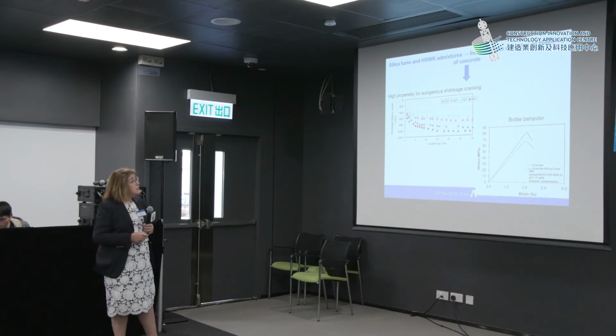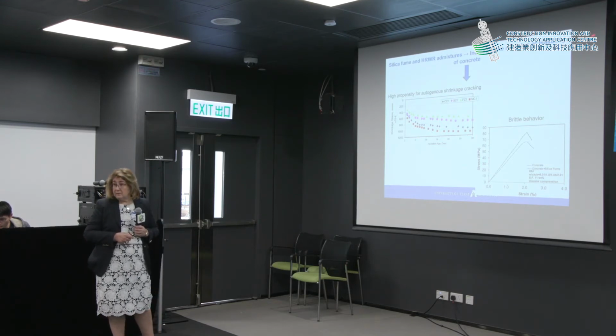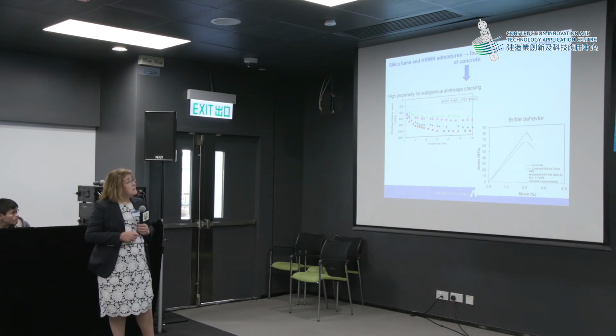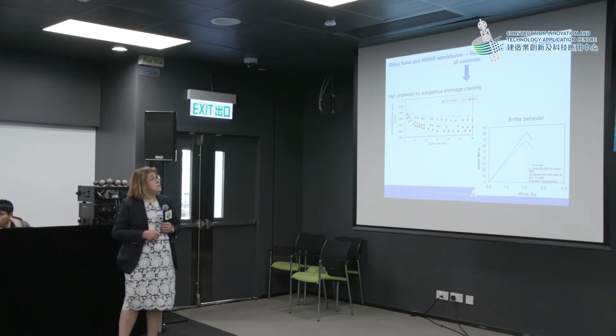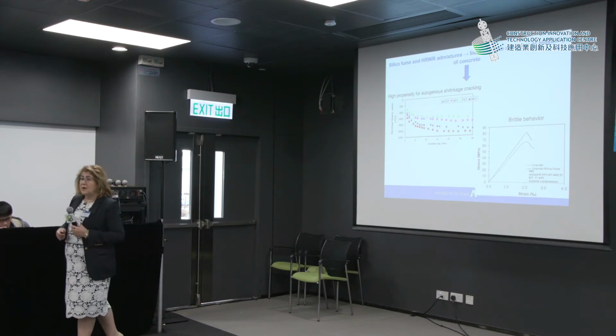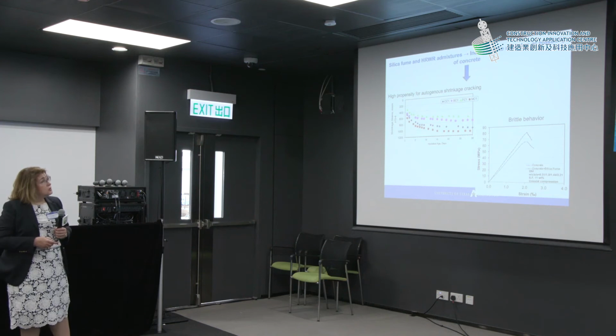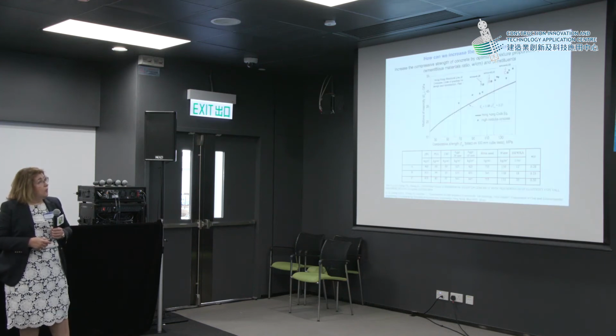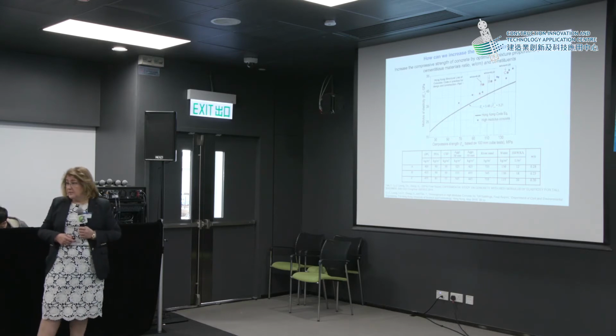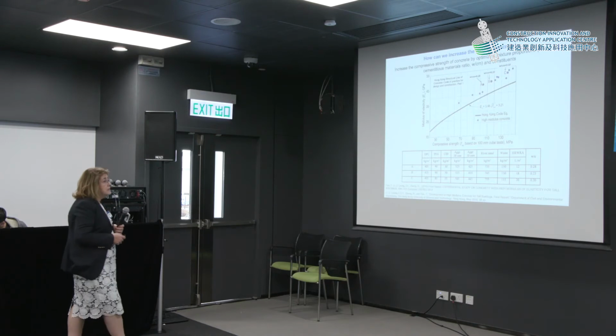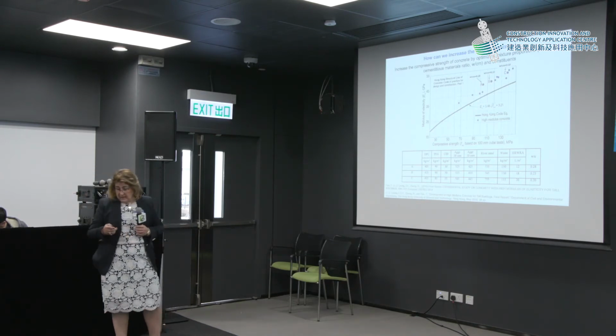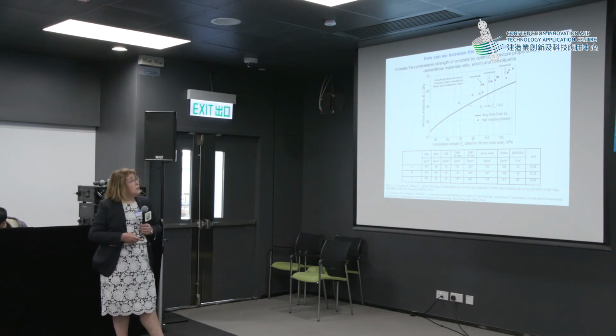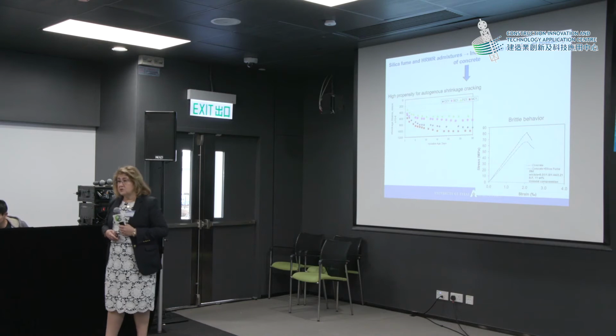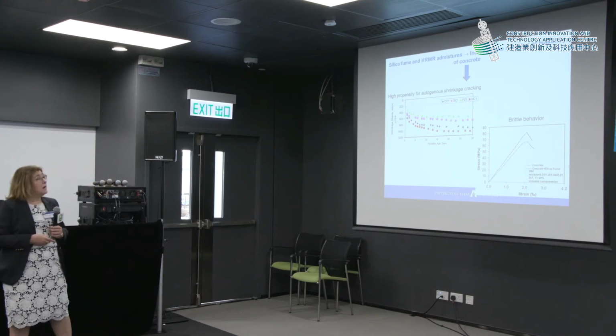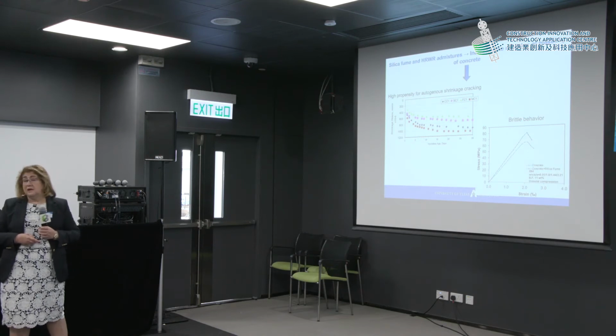Silica fume can do the magic, gives us a higher modulus of elasticity, but at the same time, it gives us a higher compressive strength, and most important of all, it gives us a high propensity for autogenous shrinkage cracking. So no matter what we try, and I can show you the previous slide again, all these mixes contain silica fume. And actually now, the modern form of silica fume would be nanosilica. But still, whatever we try, we cannot have the advantage of a high Young's modulus with a reasonable, moderate, let's say, compressive strength.